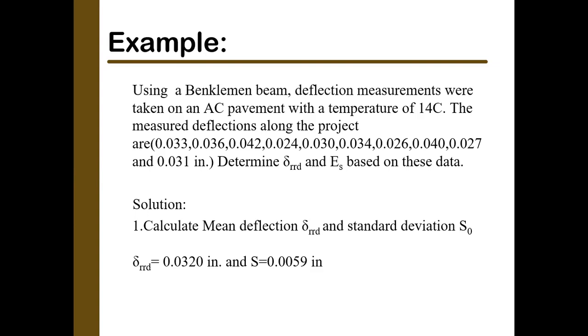So, for instance, we have taken the following. We have used Benkelman beam to measure deflection on asphalt concrete pavement. Then, at that time, the temperature was 14 degrees centigrade. The deflections were measured like 33 mils, 36 mils, 42 mils, 24 mils, 30 mils, 34 mils, 26 mils, 40 mils, 27 mils, and 31 mils. And if you multiply by 0.001, that will get the inches as has been shown in the question.